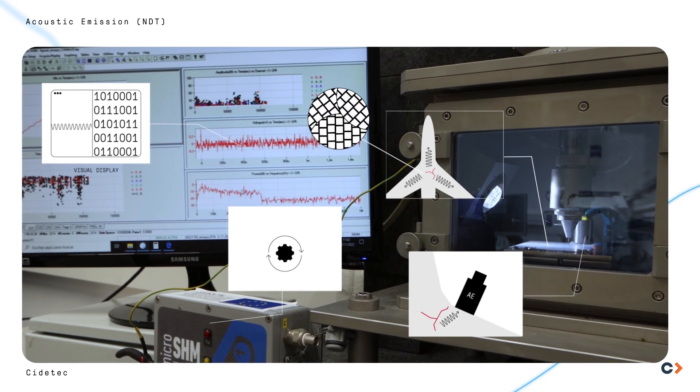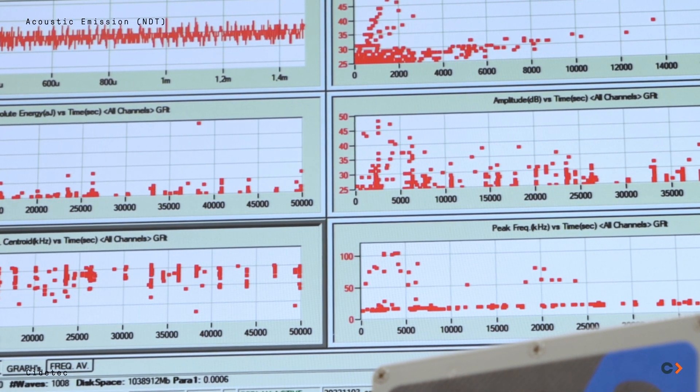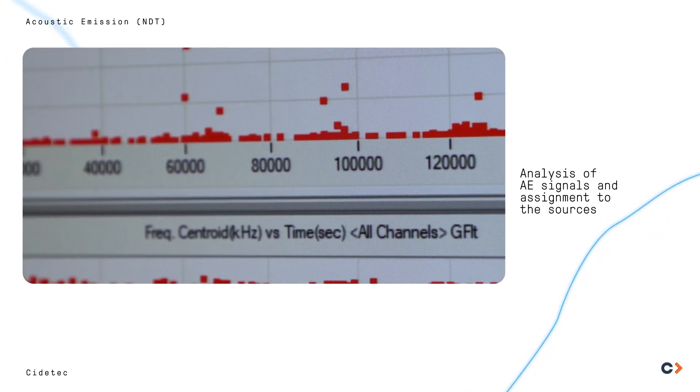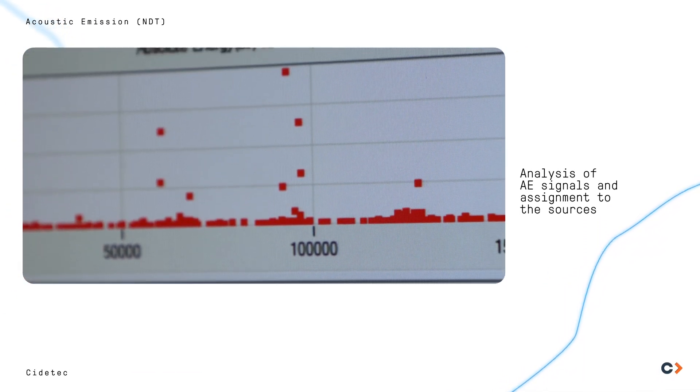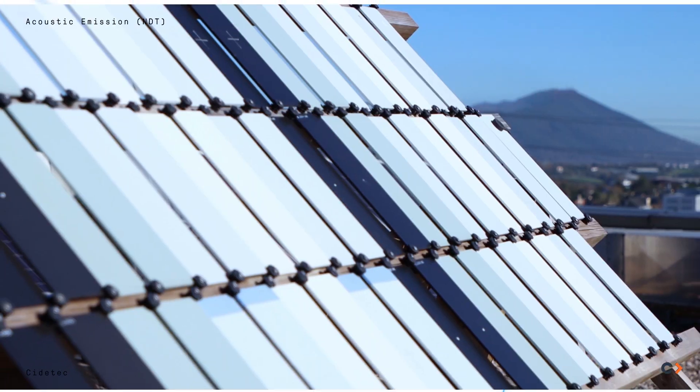After laboratory, the critical stage is the analysis of the acoustic signals, which are characterized by parameters as amplitude, duration, or peak frequency. Thanks to this data analysis and observation in laboratory, we can identify the specific signals coming from corrosion and discard unwanted noise for field application.